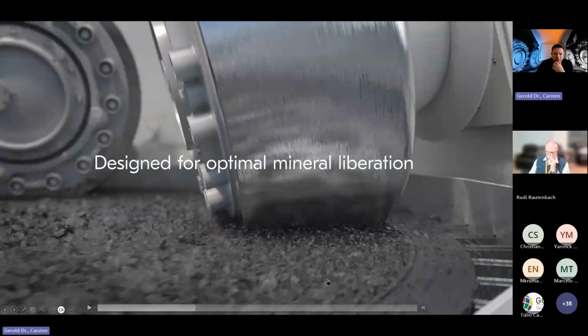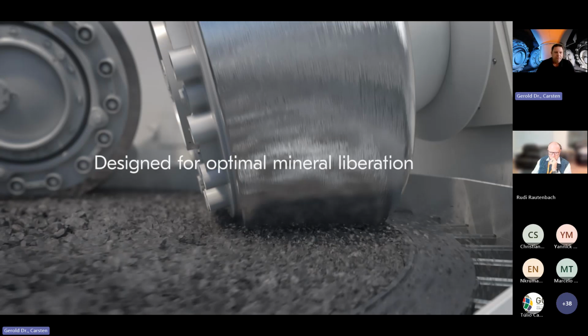Just making a short stop here because I think, especially for comminution people, this is the interesting part. So the material is fed to the center of the grinding table, and then via the speed of the table distributed to the outside below the roller. Circumferencing the grinding table on the right-hand side here to be seen is what we call the dam ring. We utilize the height of the dam ring to adjust the product particle size, respectively the retention time. And surrounding the grinding table is what we call the louver ring. This is where the gas enters the system. And just that you understand where now what is happening in the comminution zone is between the grinding roller and the grinding table.